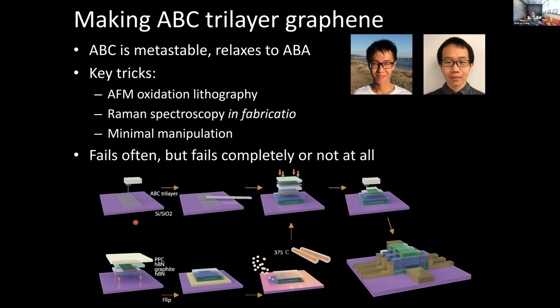So in particular, if you have mixed domains of ABC and ABA, then in the process of either heating, which happens naturally when we do our exfoliation, or in the process of further straining it even at room temperature, which happens in the process of building up these van der Waals stacks that we need in order to do our experiment, there's a sort of built-in pressure between the ABA regions and the ABC regions. So that domain wall between those always has some pressure on it. It may be pinned, but it always has some pressure on it. And after normal fabrication, you will be left with only ABA, and you won't be able to study the material you actually want. So we developed a whole set of basically process improvements for stabilizing ABC. In particular, you can cut graphite and graphene pieces out with a kind of selective oxidation using an atomic force microscope tip in a humid atmosphere.